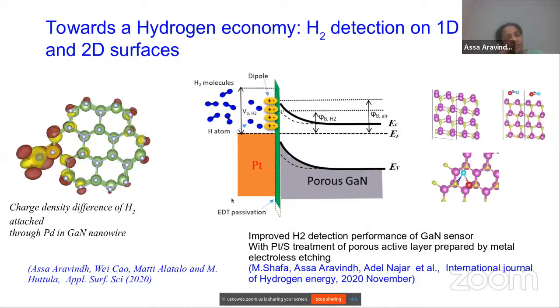Now, the hydrogen economy is in the news all the time, and many materials are being used to capture hydrogen, split it, and store it. We have also used, these are actually two different studies. On the left hand side is a purely theoretical study where we used gallium nitride nanowires, which are semiconducting. Then we doped them with palladium and platinum, which was beneficial for hydrogen evolution, because when you attach a hydrogen molecule to the bare nanowire, it stays as a hydrogen molecule itself. But when we had this metallic addition, spontaneous splitting was happening. So you don't need to provide energy to split it.